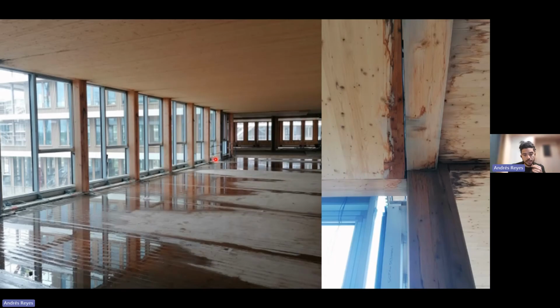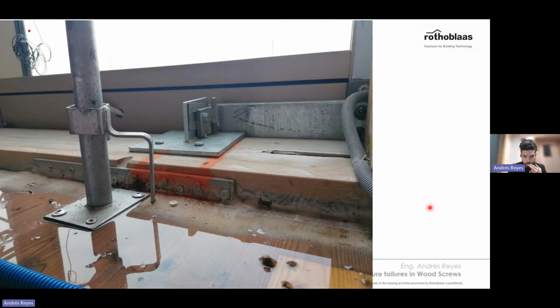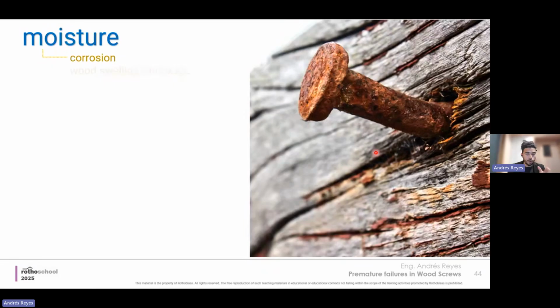And when these types of things happen, this means as well that the connections where the water tends to drain and to concentrate are the ones that suffer the most. So the conditions here, and it could be a very long period, it's very hard to say that they are dry conditions. So we're talking here about an exposure of the connections that can be very, very aggressive. And finally, here as well, we see the interaction of all those factors. So we have thick metal plates, we have improper installation, because you see here that there's at least 10 degrees, and the presence of moisture. This is a typical case where hydrogen embrittlement can happen. And if there's moisture, of course, there's corrosion.